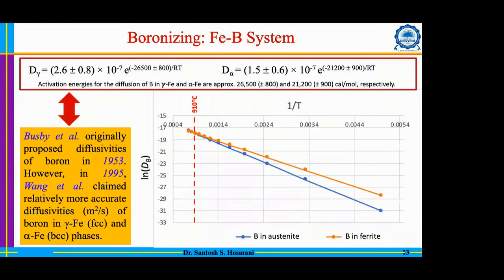Okay, so now another fundamental thing is that we need to understand the diffusion or the migration of boron in both types of lattice, whether the open structure, the BCC structure, or the close-packed FCC structure, which is the austenite structure. Here you can see that, similar to the diffusion of carbon and nitrogen in ferrite and austenite, the diffusivity of boron in ferrite is relatively faster compared to that in austenite at a particular temperature.